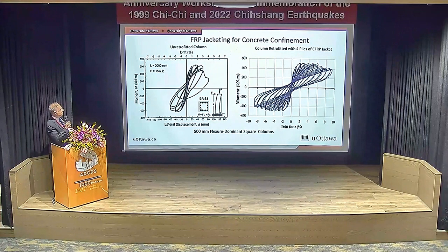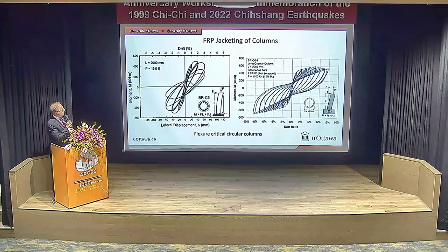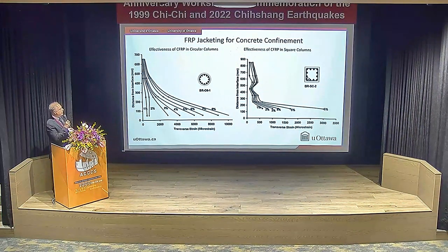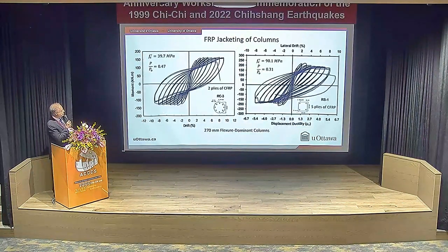And similarly, when we used square and circular columns for flexure dominant, once again with 15% axial load, we observed similar response. And these are flexure critical circular columns, with substantial improvement because here the predominant mode was flexure. Once again, when you look at strain levels measured, they're all very low. We did not fully utilize it, so one would obviously not take the entire full strength because it doesn't have the ability to confine as the column dilates laterally.